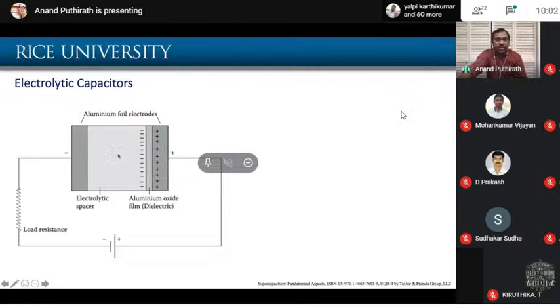And if you apply charge across it, this is how the charge forms at the interfaces. Positive charge here, and you have the aluminum oxide dielectric, and then negative charges from the electrolyte will accumulate here. So this is a capacitor. And probably you will have a small capacitance at this layer also, but that will be slightly less compared to here, because the separation here is of the order of 0.013 micrometer or something.